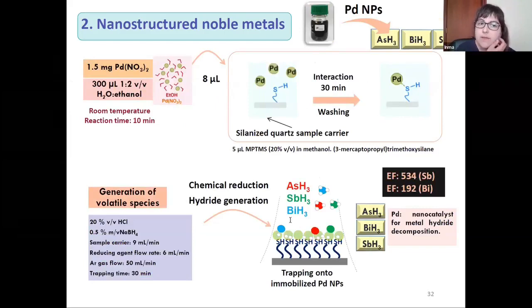In a similar work, we have these palladium nanoparticles, in this case prepared by reduction of palladium 2 as palladium nitrate in the presence of ethanol-water. After reduction of these nanoparticles, they were prepared in a silanized quartz sample carrier using the same silane as in the previous work. After interaction during 30 minutes, the film was washed, allowing only to have the palladium linked to the silane. Then the volatile species were generated, in this case, with a more concentrated acid and a similar concentration of sodium borohydride. In this case, the hydrides of arsenic, antimony, and bismuth were generated, and this vapor was trapped onto the palladium nanoparticles, also retained by catalytic decomposition of the metal hydrides, as in the case of selenium.